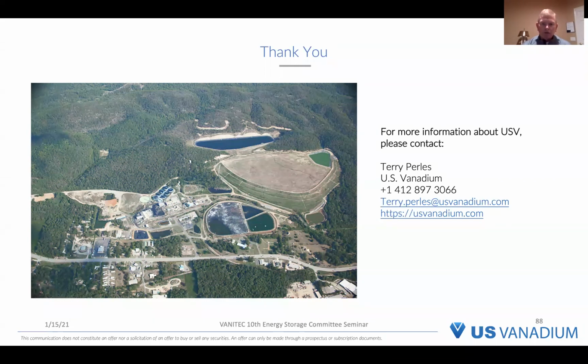When you talk about electrolyte, of course, every battery company has a different specification, but we can say very generally that the requirement for the electrolyte is fairly severe. The allowable levels of impurities, and we're talking about, I don't know, half the periodic table here, are very low. In some cases, single digit parts per million or less. And so the quality is important. And so this is a situation where you see the chemical industry, the titanium industry, and the energy storage industries really have very different needs for vanadium from a quality standpoint. And there's not that many producers in the world that are set up to produce very high purity oxides that can be used in electrolytes.